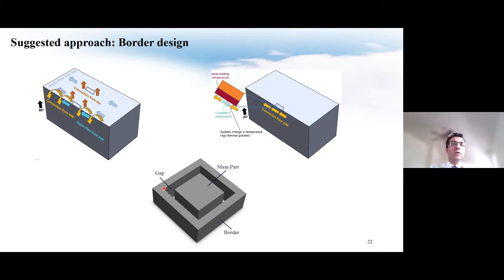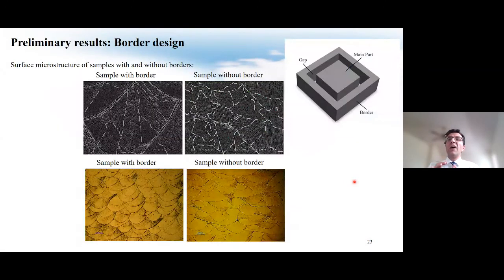So by considering this border as presented here, our preliminary results demonstrated that adding a border with a gap of about 0.5 millimeter significantly controlled the microstructure variation in SLM fabricated nitinol parts. For example, the sample processed with a border demonstrated larger epitaxial, we can say equiaxed grain and more intense melt pools. The future direction on this topic is to further optimize the gap between the border and the main parts and perform mechanical and fatigue tests to obtain the level of improvement in the mechanical strength of as-fabricated superelastic nitinol.